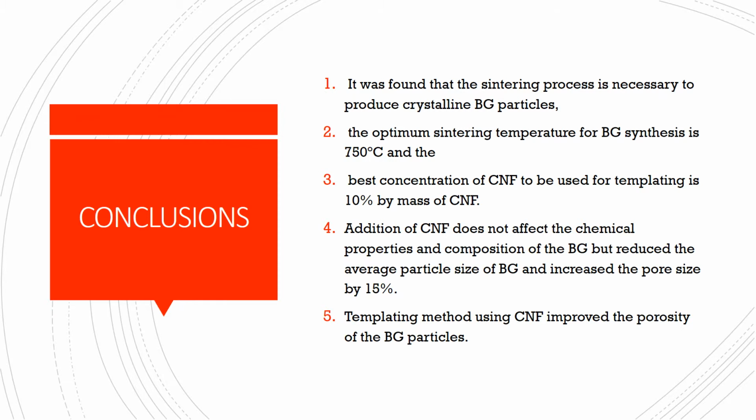In conclusion, it was found that the sintering process is necessary for the production of crystalline bioactive glass particles. The optimum sintering temperature for bioactive glass synthesis is 750 degrees Celsius. The best concentration for CNF to be used for templating is 10% by mass of CNF.